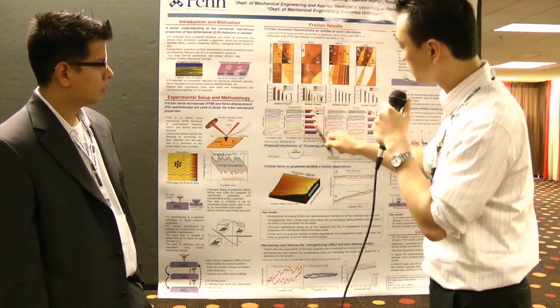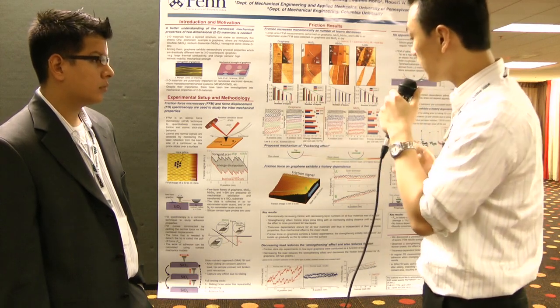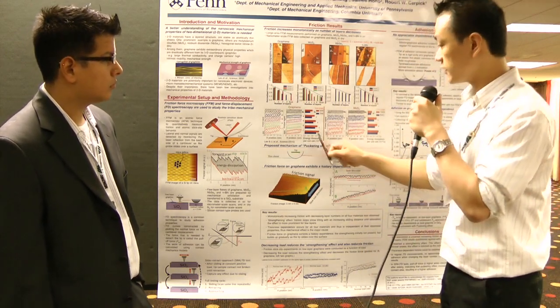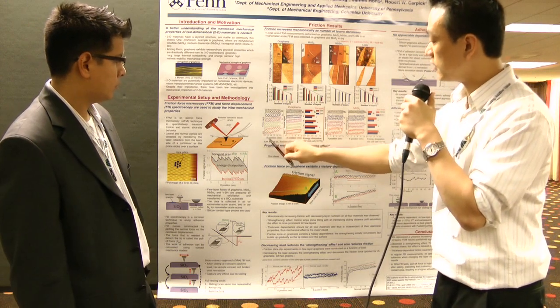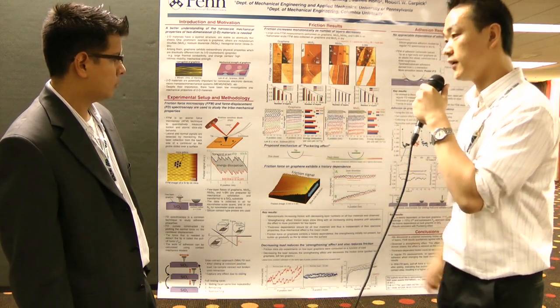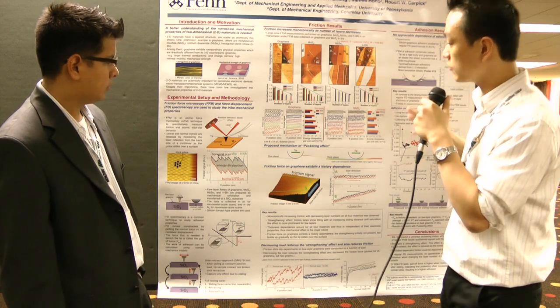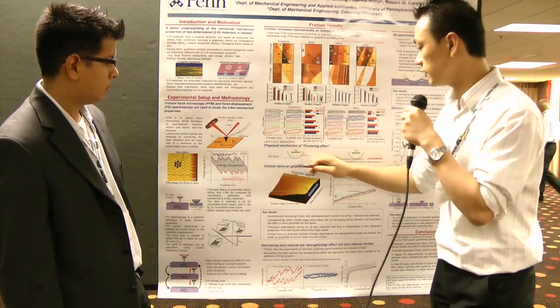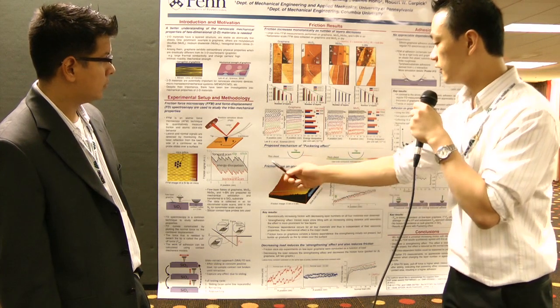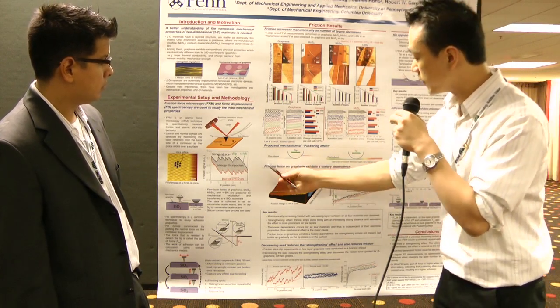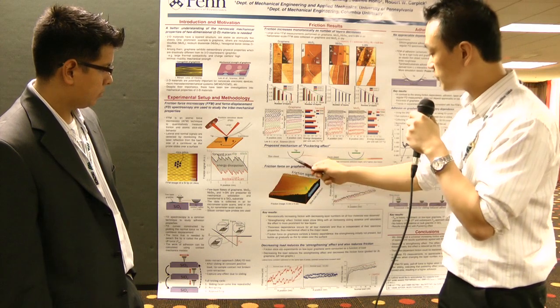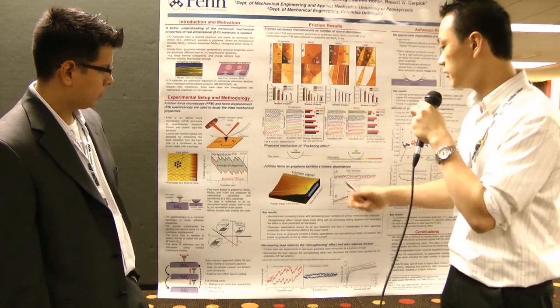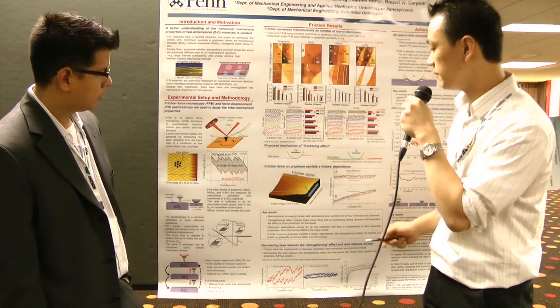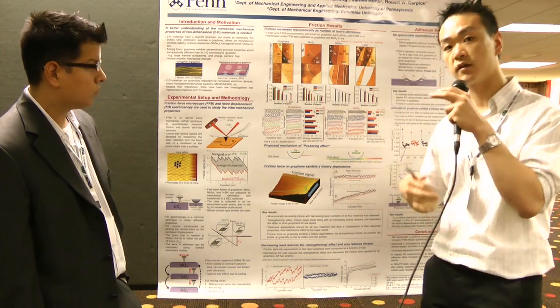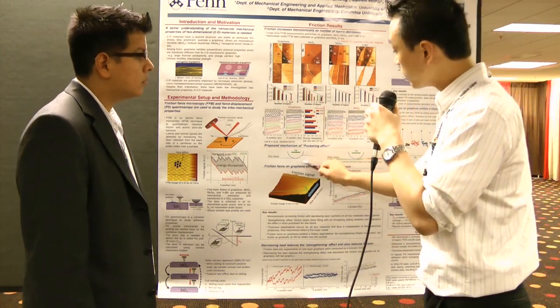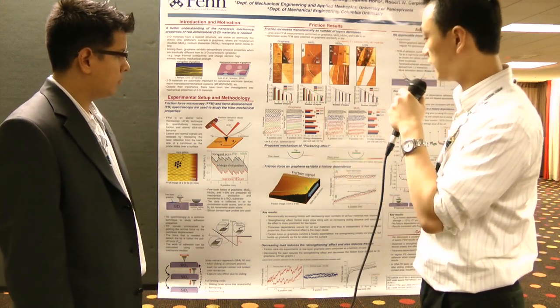If you see the friction, which is related to the amount of energy that's dissipated, the thinner the sheet, the more energy you're dissipating. That's pretty striking, and we think it's related to the so-called puckering effect, which you can see in the following. If the sheet gets thinner, you have a higher area that's puckering because of sliding of the AFM tip. Since this area is creating a larger contact area, we therefore measure higher friction, and we see that on all these materials.